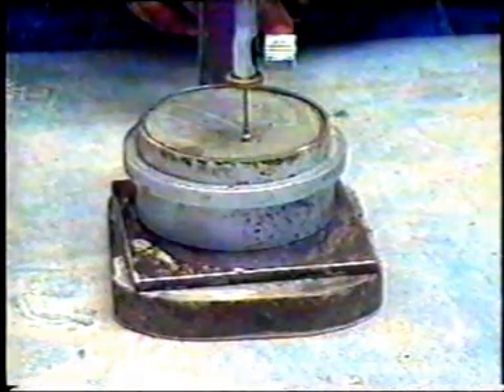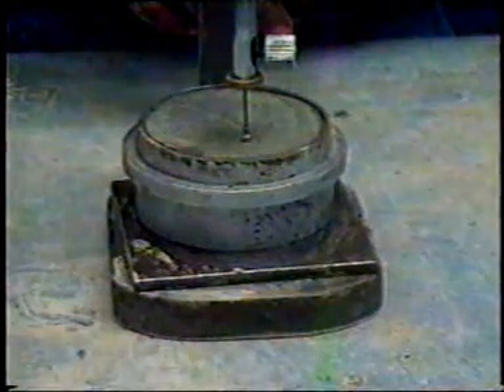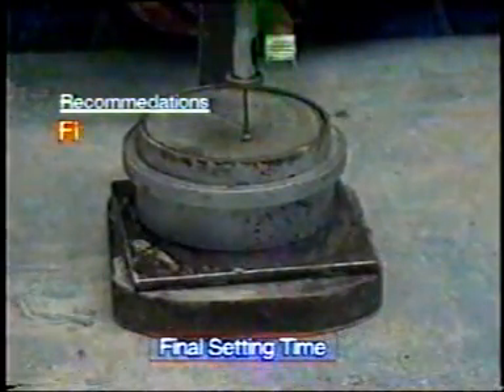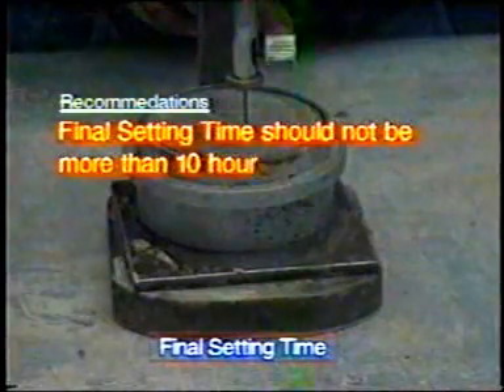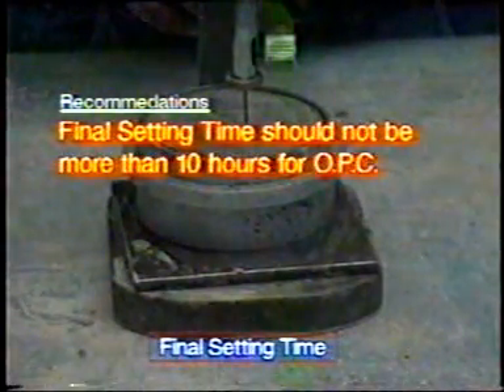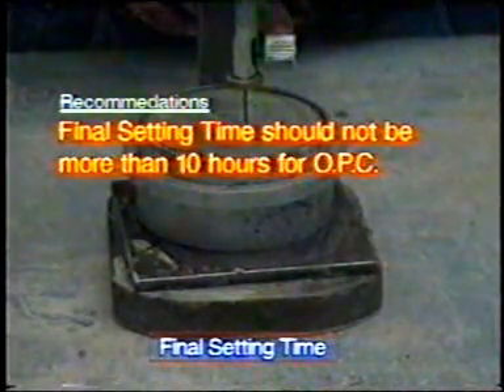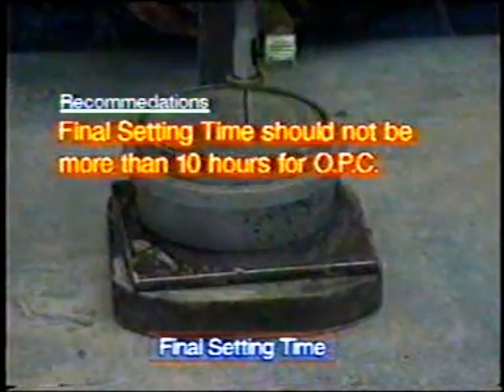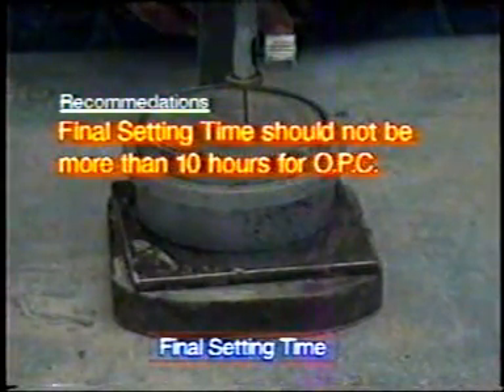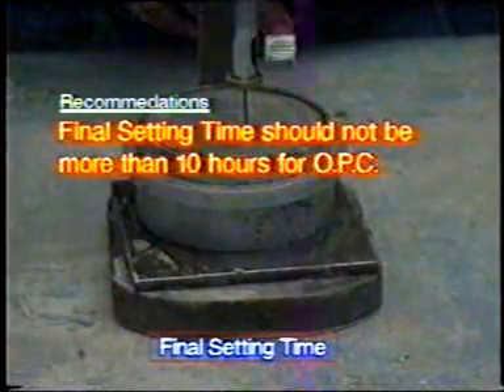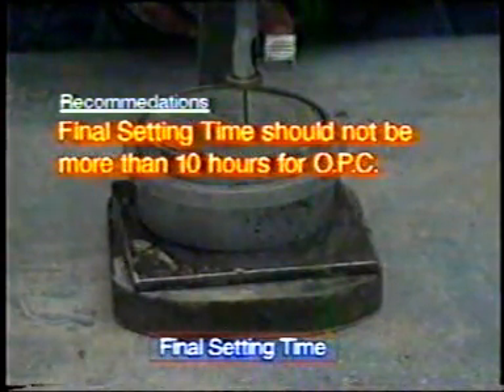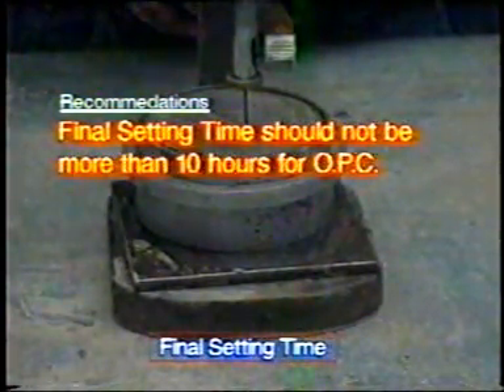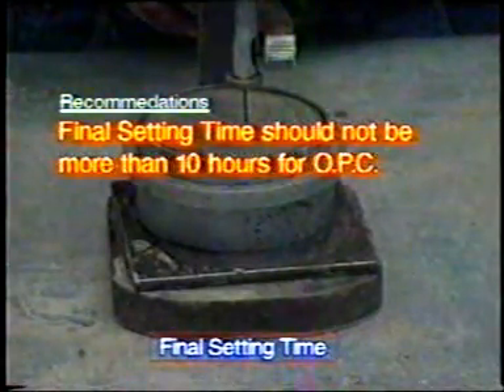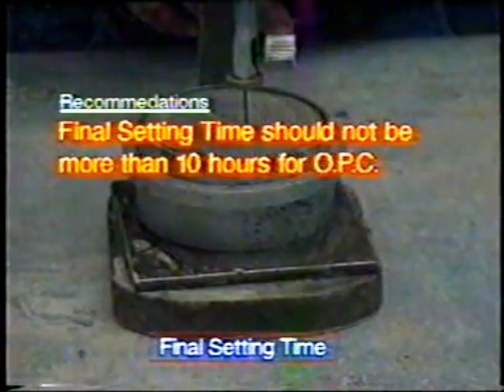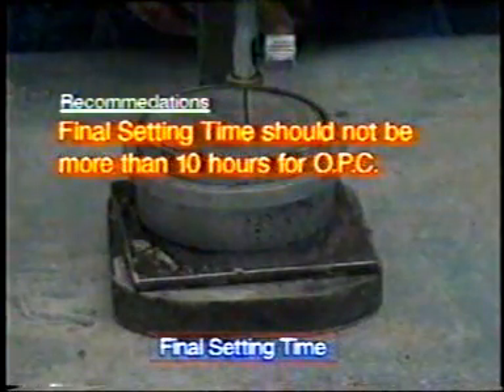Report the period elapsed between the time when the water is added to the cement and the time at which the needle makes an impression and the outer ring fails to do so as the final setting time. Recommendations. The final setting time should not be more than 10 hours for ordinary Portland cement.